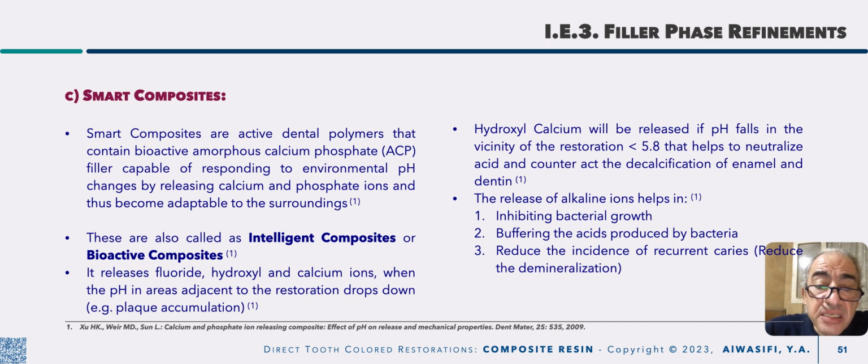The release of these alkaline ions will help in inhibiting bacterial growth, buffering the acids produced by bacteria, and reduce the incidence of recurrent caries by reducing the demineralization effect. That's why it is called intelligent composites or bioactive composite. But also, it undergoes disintegration and biodegradation of the material contents. That's why its physical properties will be affected negatively by time, and the clinical longevity and serviceability of the material is a little bit questioned.